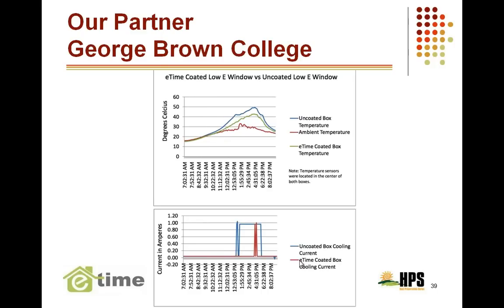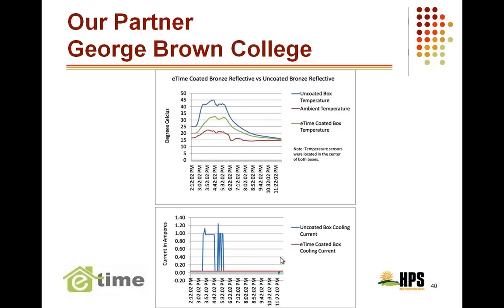On a low E window, we were still about 8 to 11 degrees difference between the two. It's about 50 to 42 degrees. So we're able to understand more fully that this is working on all different types of windows. No matter what they are, they're going to have an effect. As far as the cooling load is concerned, you'll notice it's very dramatic. It would probably be about 4 to 5 times more on the uncoated side versus the coated box. You would see the refrigeration units kicking in. Now, the last one is the biggest surprise to me. That was the reflective bronze coating.